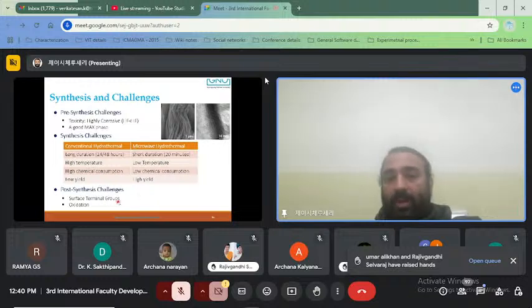The second problem is with the storage of the MXene, that is, the oxidation. For example, we prepared titanium aluminum carbide as the MAX phase, then synthesized the titanium carbide MXene. Now I want to store this material. Even if you dry the material, it will get oxidized. You can see white spots on the black material.